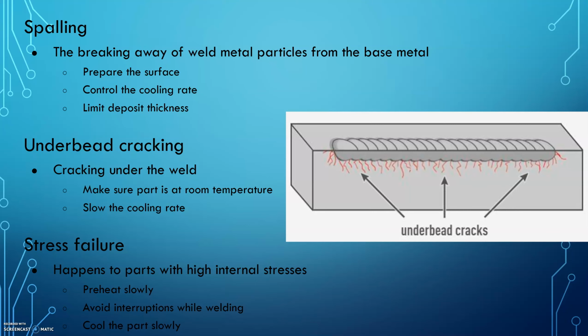Page 11, spalling is the loss of weld metal from the base metal due to cracking. Controlling the cooling rate and limiting deposit thickness will help reduce spalling. Underbead cracking usually happens in the heat affected zone in low and high alloy steels. Stress failures are usually found at the toes of welds.